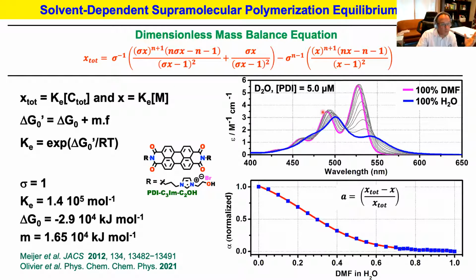And so if you look at the spectrum in pink here, these are again spectroscopic signatures of fully dissolved PDI units. And of course, as I am incrementing the solution with water, essentially to go almost to 100% water, what I'm gonna have is this rebalancing of my 0,0 and 0,1 transitions. So from molecularly dissolved to aggregated. And of course, we can apply a dimensionless mass balance equation to fit the degree of aggregation as a function of DMF in water. And we extract somewhat the same thermodynamic parameters that I've showed you before, as well as the degree of polymerization. But again, this slide is also to show you that a subtle change of global solvent dielectric will obviously have a huge impact on the optical properties of this nanoscale object.